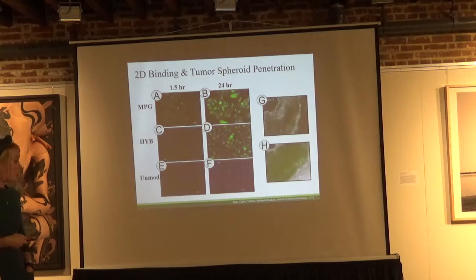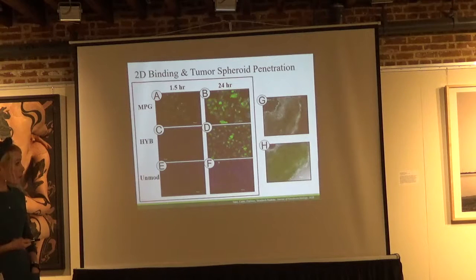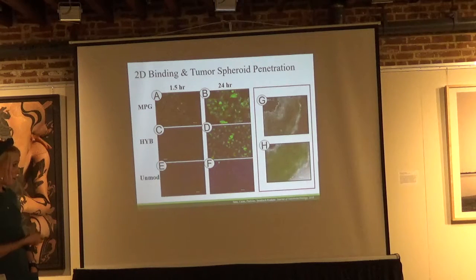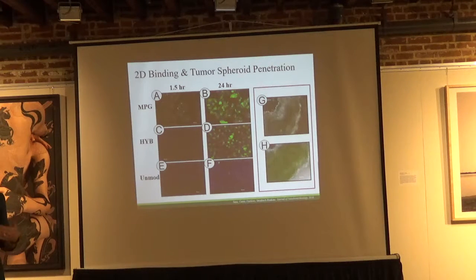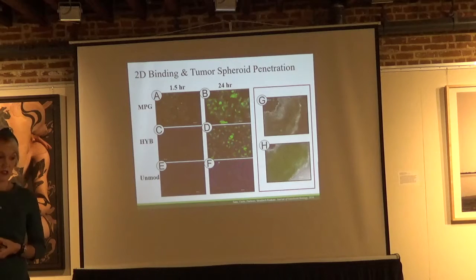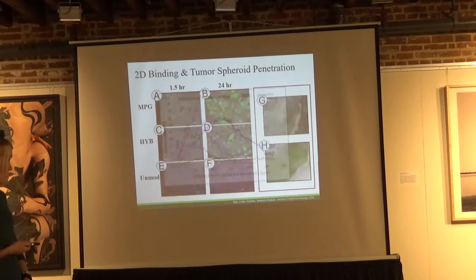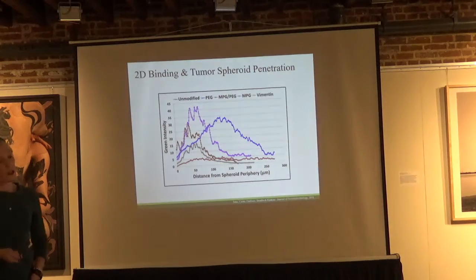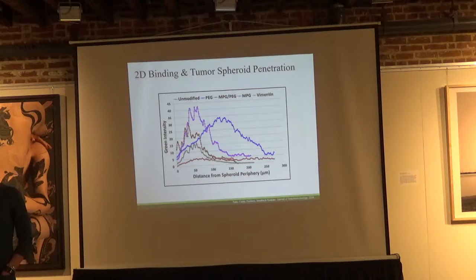So we looked at these in 2D assays, and we saw increased uptake using MPG or hybrid MPG stealth particles after 24 hours. And then moreover on the right, we tested some of these, so MPGs in panel H relative to unmodified particles in the actual tumor spheroid in G, and we could see increased localization and association with the tissue after this modification. What we really wanted to look at is how far could we get as a function of modification, how far could we actually get these particles into the tumor spheroid matrix.